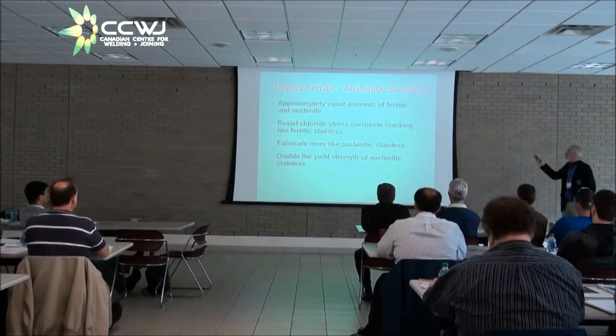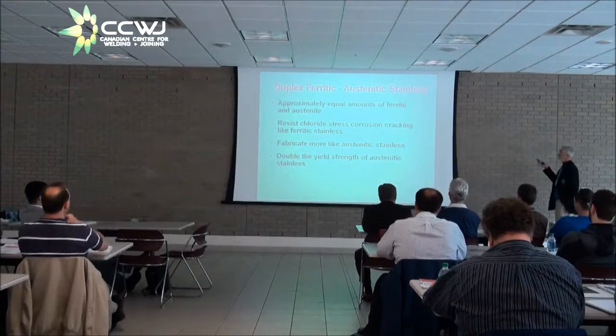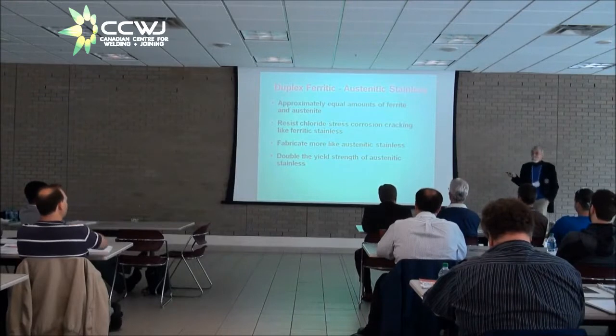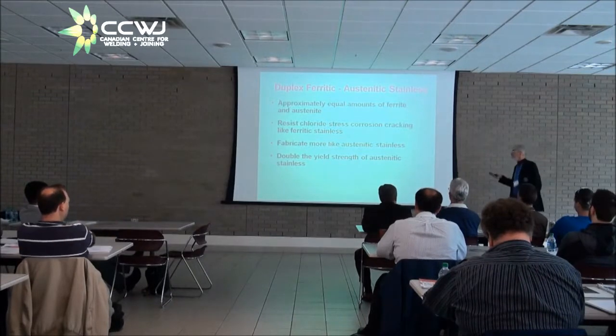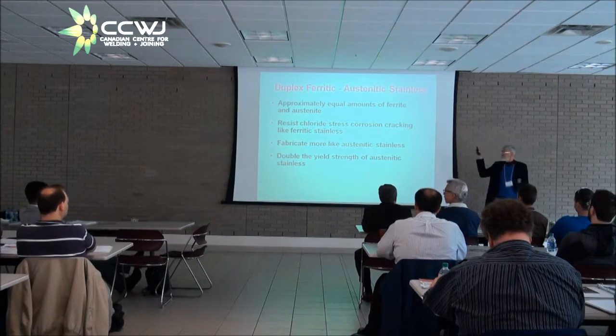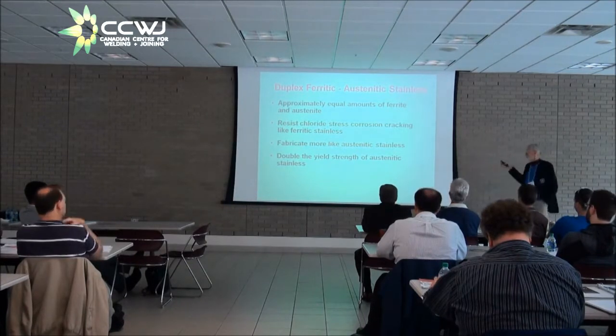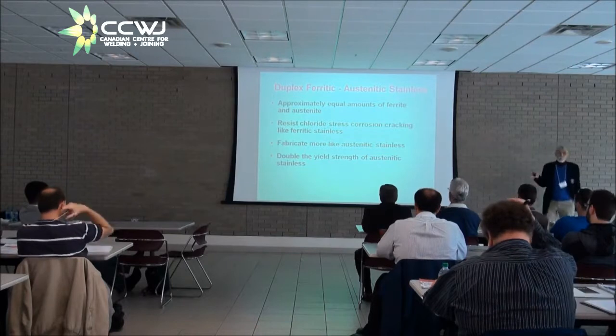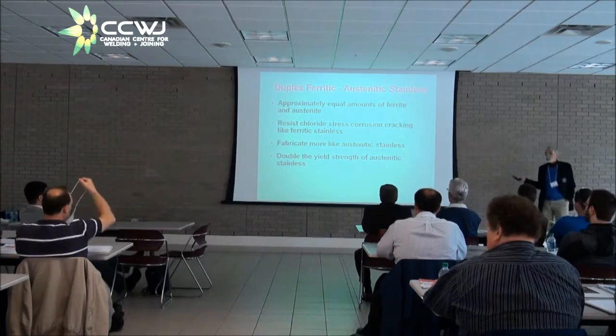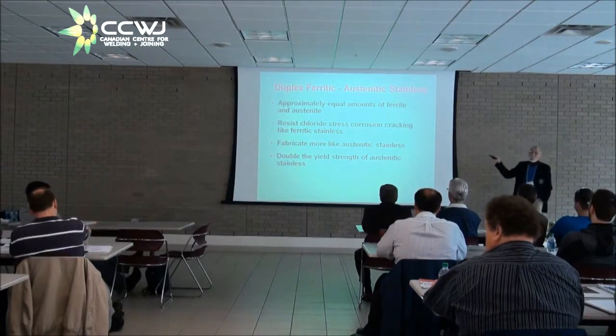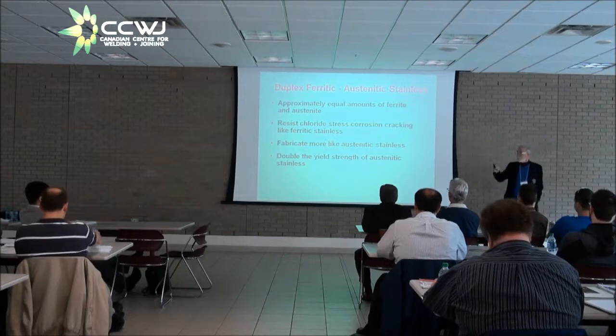Okay, so in a duplex stainless steel, you've got approximately equal amounts of ferrite and austenite. Some say 50-50 or something like that. These give you resistance to chloride stress corrosion cracking like the ferritic stainless steels. They give you fabrication properties that are more like austenitic stainless steels, and they give you a bonus, a doubling of the yield strength. That was already mentioned before.